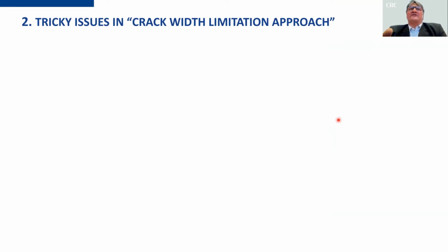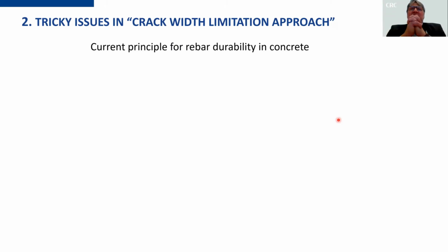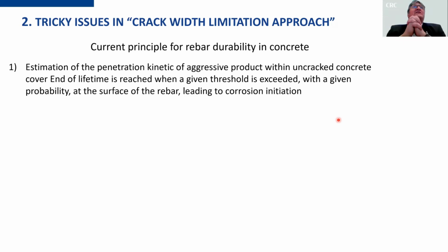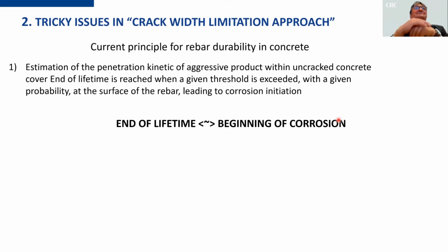Also, there are tricky issues with the crack width limitation approach. The current principle for rebar durability in concrete is more or less the following. First, we suppose the concrete uncracked. And then we estimate the kinetics of the penetration of aggressive products in the concrete. And the lifetime is reached when the aggressive agent reaches the rebar. This approach leads engineers, designers, controllers to think that end of lifetime is more or less equivalent to beginning of corrosion.